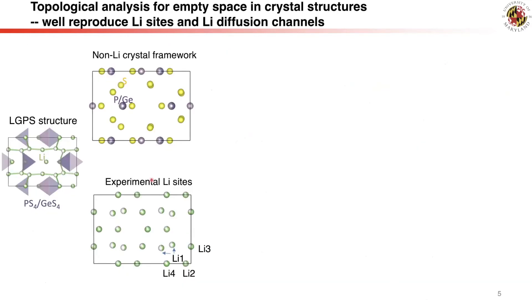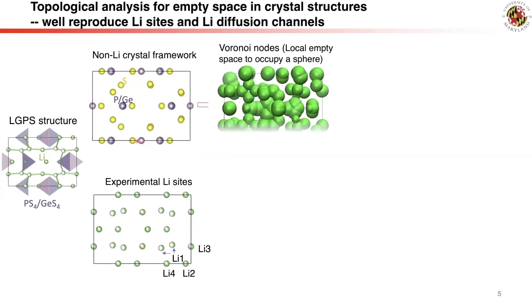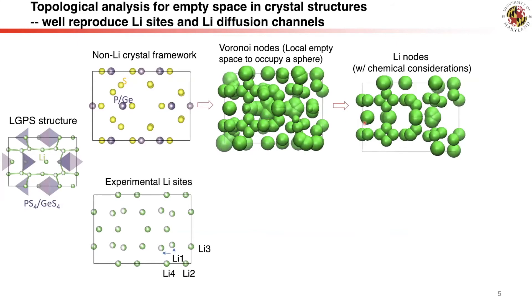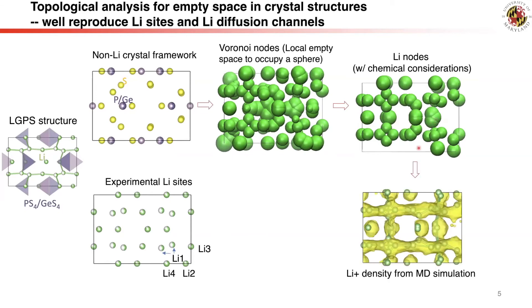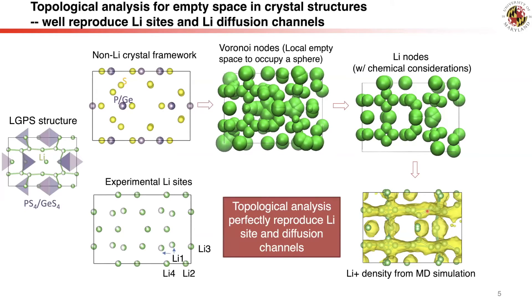We use topological analysis, applying Voronoi nodes as the empty space in the crystal structure framework. We then down-select them by bond valence and cation distance, which provide a suitable chemical environment to occupy lithium. This simple analysis reproduces lithium sites in the LGPS structure from experiments and also gives the lithium diffusion pathway in agreement with ab initio molecular dynamics simulations.